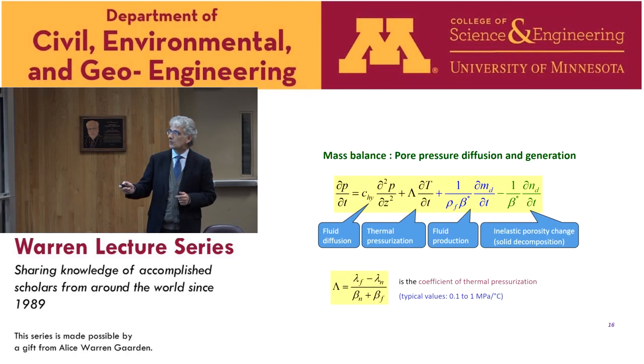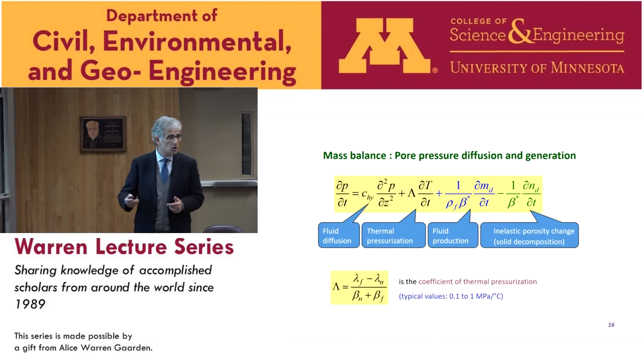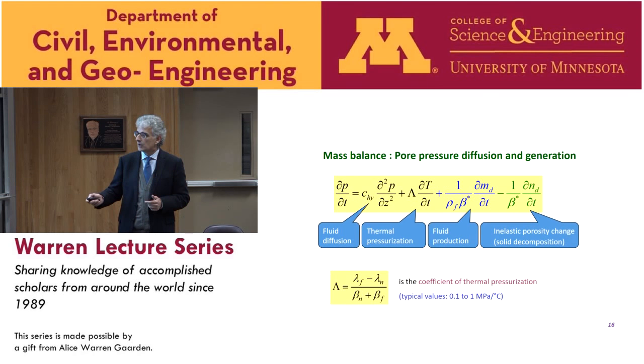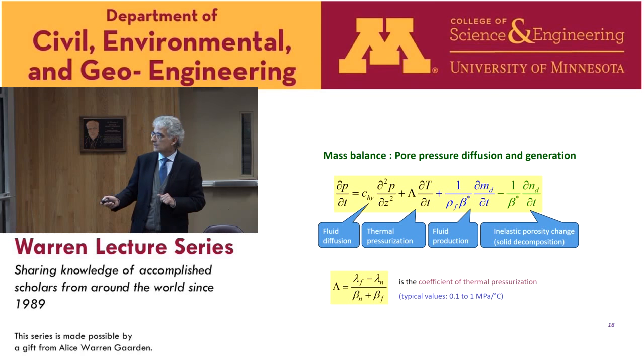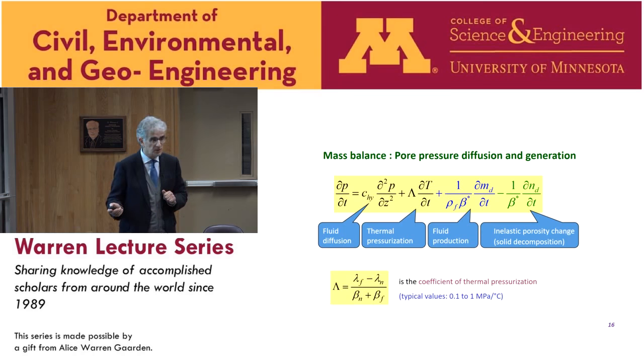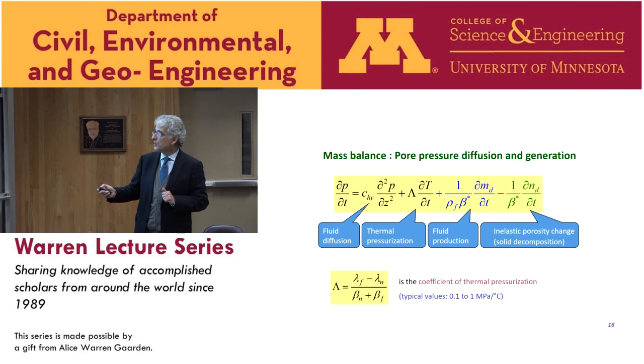The mass balance for the fluid, which gives the pore pressure diffusion and generation equation. In the right-hand side, we recognize the term for the fluid diffusion. This is a source term, which is the thermal pressurization term. Lambda is the coefficient of thermal pressurization, which in thermo-poro-elasticity is expressed as, in the numerator here, the difference between the thermal expansion coefficient of the fluid minus the one of the porous medium. And in the denominator, we have the sum of the compressibility of the porous volume plus the compressibility of the fluid. And this coefficient has typical values of between 0.1 to 1 megapascal per degree. So this is the source term. If we have chemical reactions, we have fluid production, which is an additional source term. And this is the term corresponding to the inelastic porosity change, for example, due to solid decomposition.